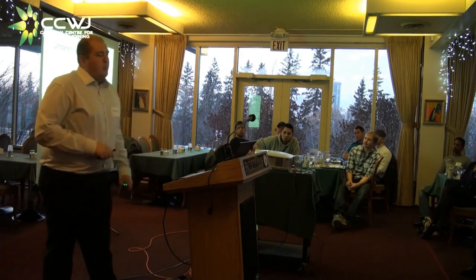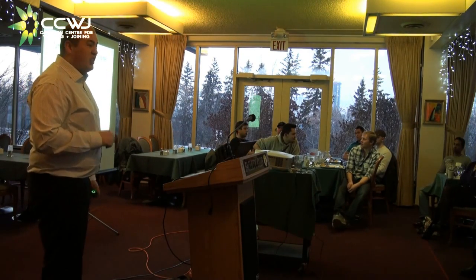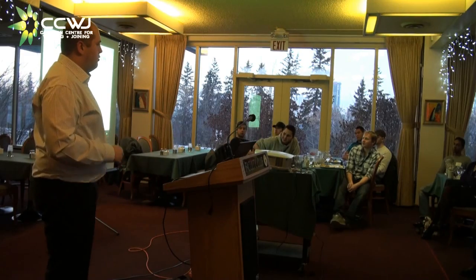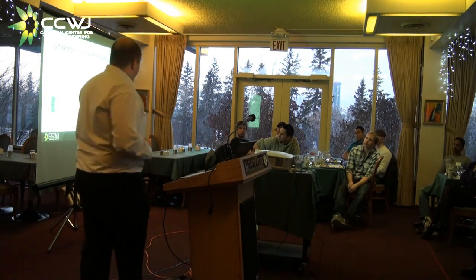The Japanese right now are using it to weld sheet metal for automobiles. And they can actually weld with this process fast enough that the robots cannot move any faster. They've maxed out robots. They can weld so fast. But the thing is, we're not using a steel consumable anymore. We're using a tubular nickel tungsten carbide consumable. And that gives us a couple brain cramps.